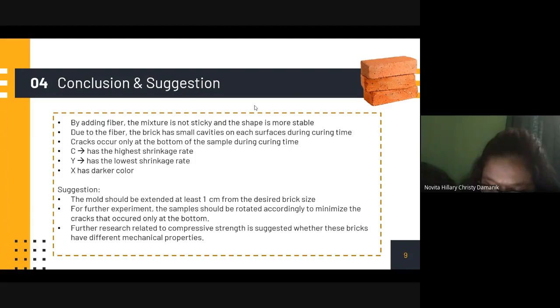There are also some suggestions for the next research that should be considered in making unfired clay brick. The first one, the mold should be extended at least 1 centimeter from the desired brick size. And in further experiments, the sample should be rotated accordingly to minimize the cracks that occurred only at the bottom during the curing time. Further research related to compressive strength is suggested, to see whether these bricks have different mechanical properties.